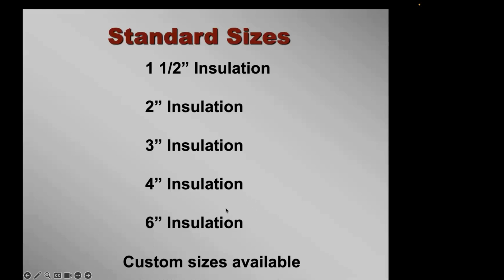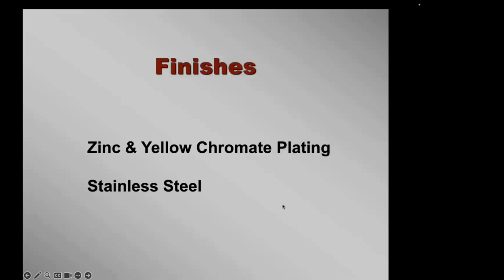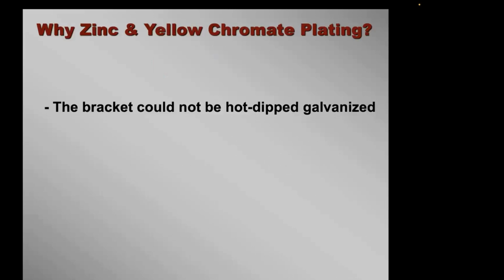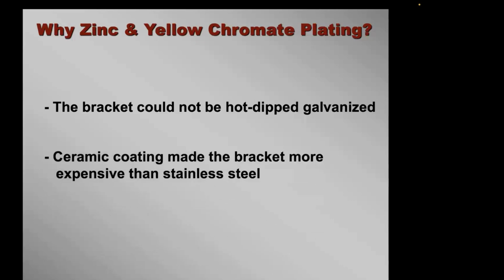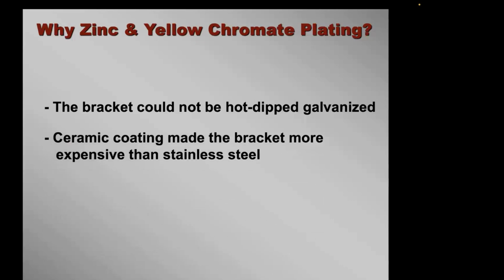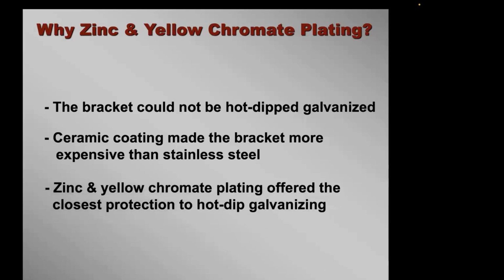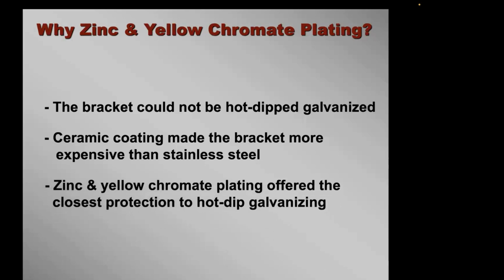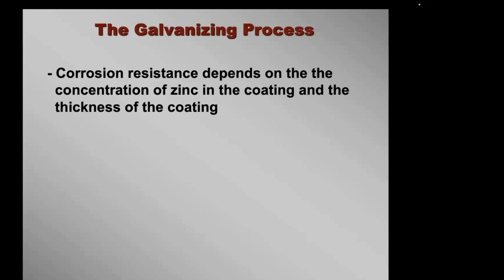I have a job in fabrication right now. It's one and a half inch insulation, so I can do any size on that. The finishes I offer are zinc and yellow chromate plating and stainless steel. Why did I do zinc and yellow chromate plating? Because I wanted hot dip, but it wouldn't work. The parts wouldn't screw together after hot dip galvanizing. Ceramic coatings make the bracket more expensive than stainless. So the zinc and yellow chrome plating offered the closest protection to hot dip galvanizing that I could get.